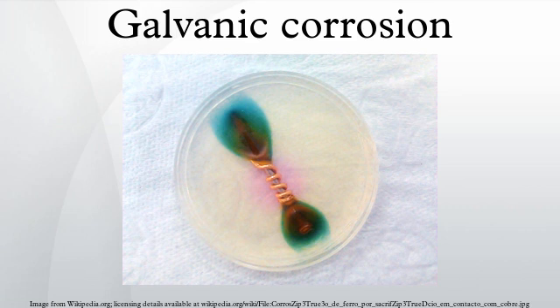U.S. Navy Littoral Combat Ship Independence: serious galvanic corrosion has been reported on the U.S. Navy attack Littoral Combat Vessel USS Independence, caused by steel water-jet propulsion systems attached to an aluminium hull. Without electrical isolation between the steel and aluminium, the aluminium hull acts as an anode to the stainless steel, resulting in aggressive galvanic corrosion.